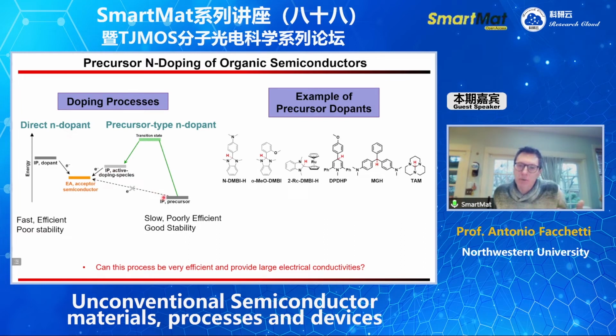This process results in molecules which are more stable. The process is more controllable, but typically it's a very slow process and typically poorly efficient. There are many types of precursors and dopants. These are some examples of the class. And in this type of dopant, the doping species is associated to the cleavage of this carbon-hydrogen bond. And the bond gets cleaved primarily heterolytically, so with formation of hydride.